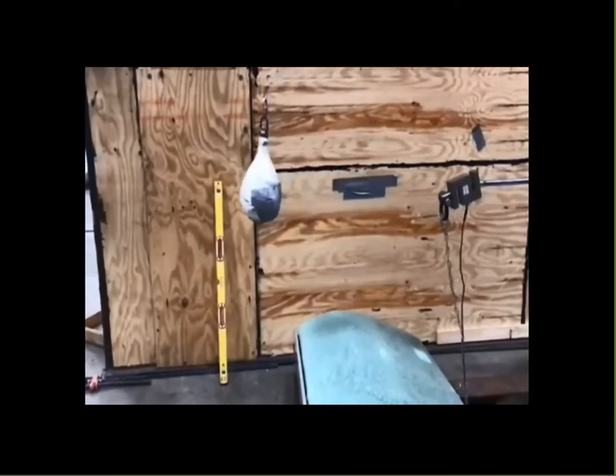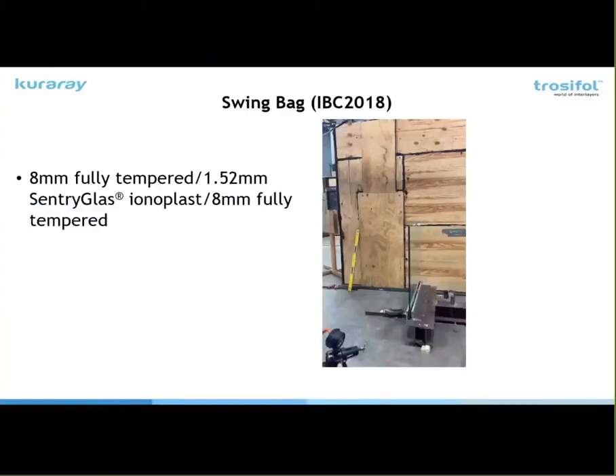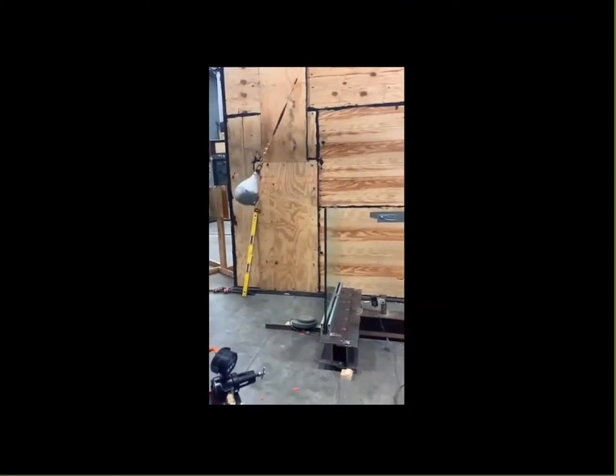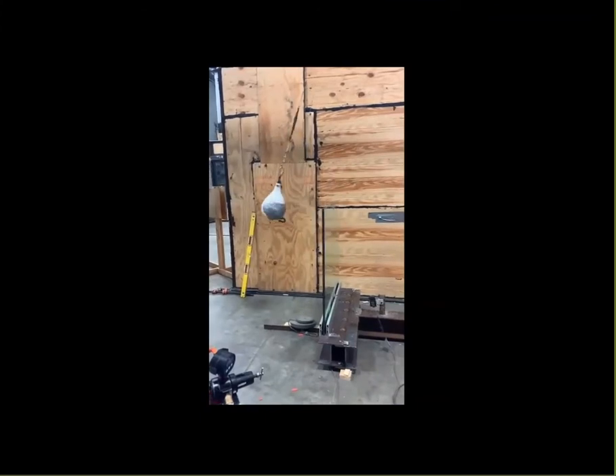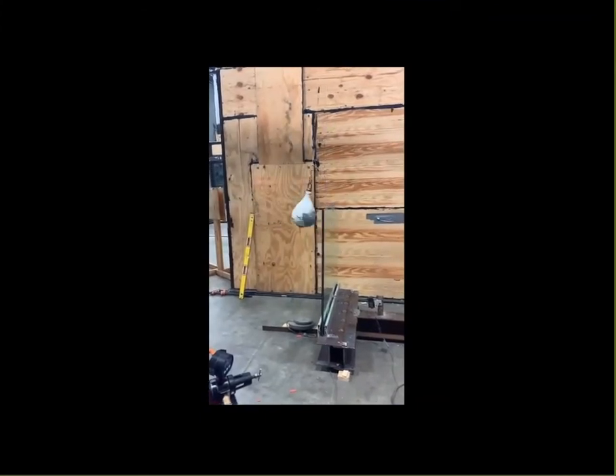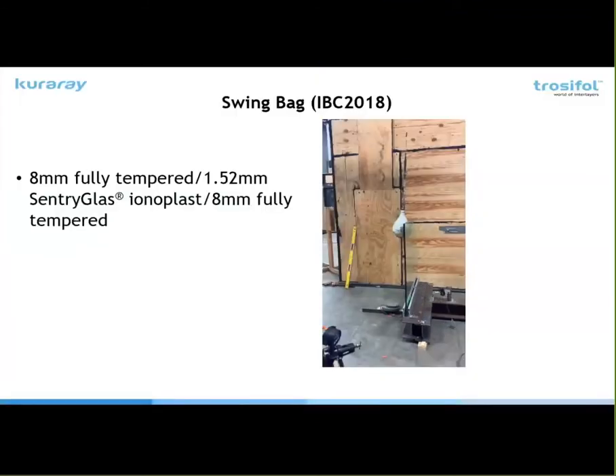So then we've done it with SentryGlass, again with 8 millimeter glass. It's impacted and it did not break. We were pretty impressed by this. Now, that being said, you can't go out and say, okay, I'm going to specify 8 millimeter glass and 60 mil SentryGlass interlayer, and I don't need building official approval. The railing supplier has to test the system, and the system has to pass.